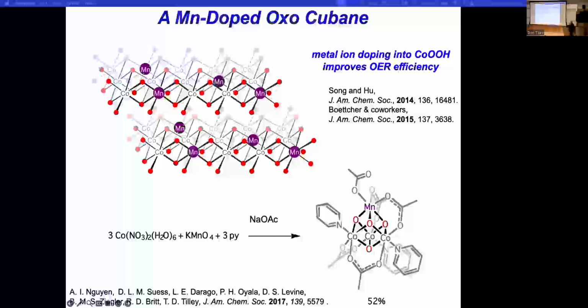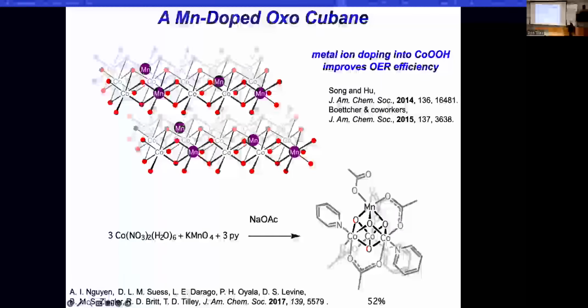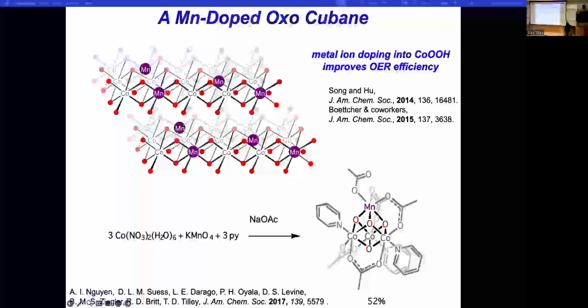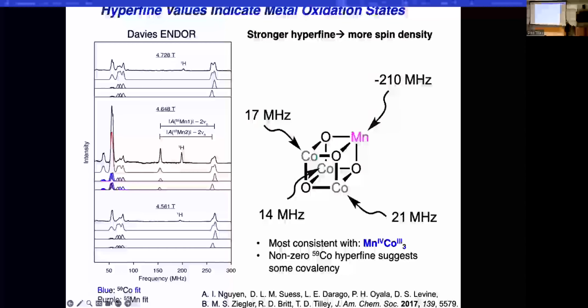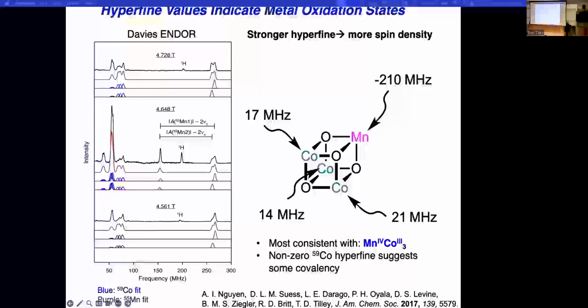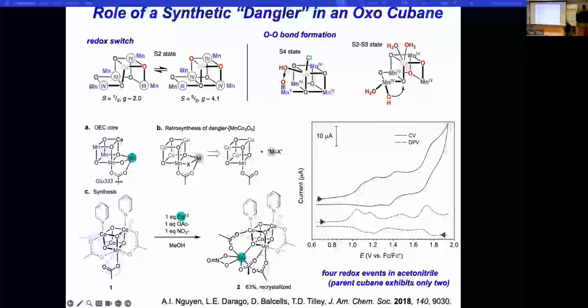So it gives a 52% yield of this manganese tricobalt cube, which we need to study more, but in collaboration with Dave Britt, we were able to see that the spin density on this manganese is coupled to the cobalts. So there is some spin delocalization, albeit small, in cubes like that.